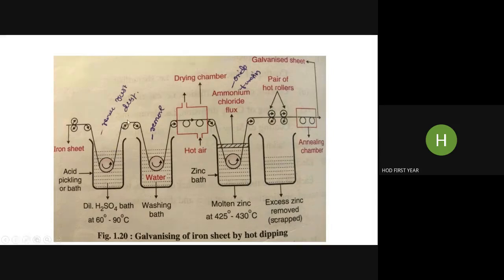Then the sheet is passed into water to remove that acid and impurities, the washing bath. Then it is passed into a drying chamber to remove the water and acid. Then these dried sheets pass into the zinc bath, molten zinc bath. Here we have molten zinc maintained at around 430 degrees Celsius. Here we get a uniform coating on the metal article. Here you will see the layer of ammonium chloride to avoid oxidation of zinc. Because zinc is in molten state and at high temperature, it easily reacts with oxygen of air. So to avoid air oxidation, that bath is usually covered with ammonium chloride flux.